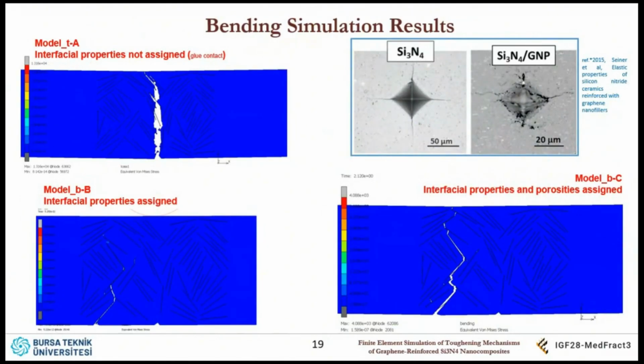And as you see, this is an experimental result. You see, this is monolithic ceramic. The crack path is very straight, but here it is like zigzags. So this model is not valid. So the connection between the graphene and matrix should be weaker than the connection between the grains of ceramic. So this study supports this information also given in the literature.